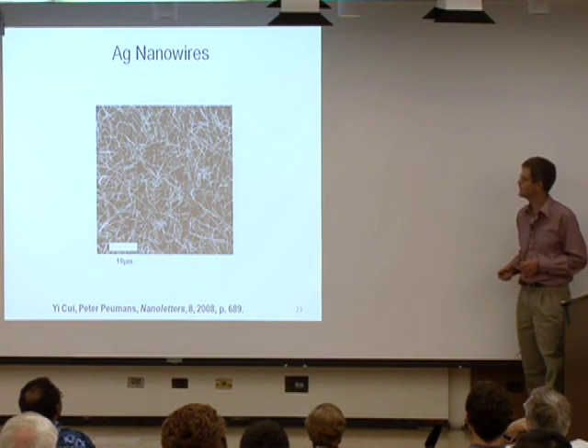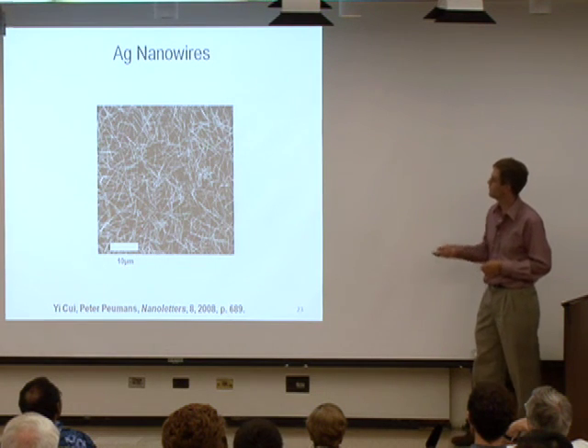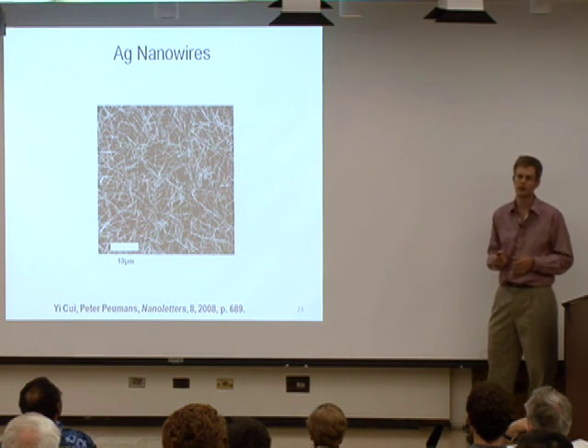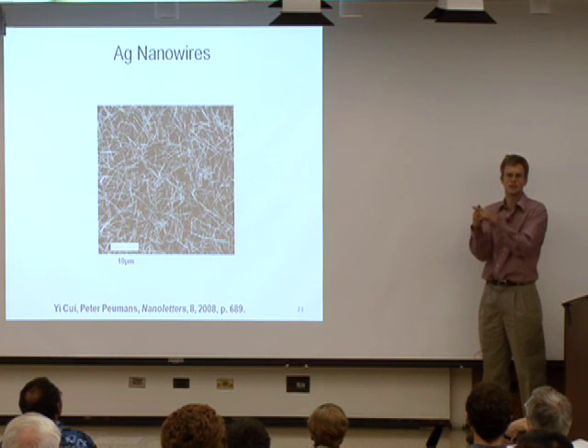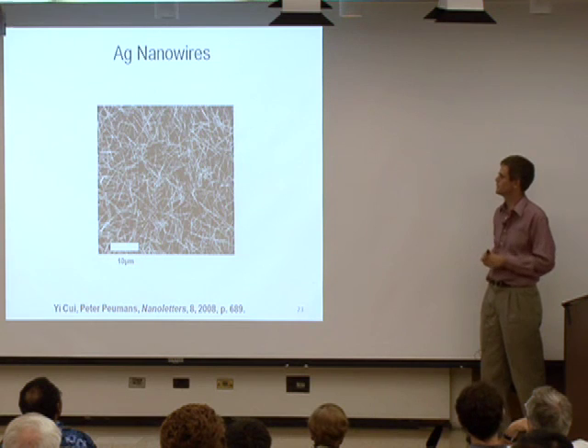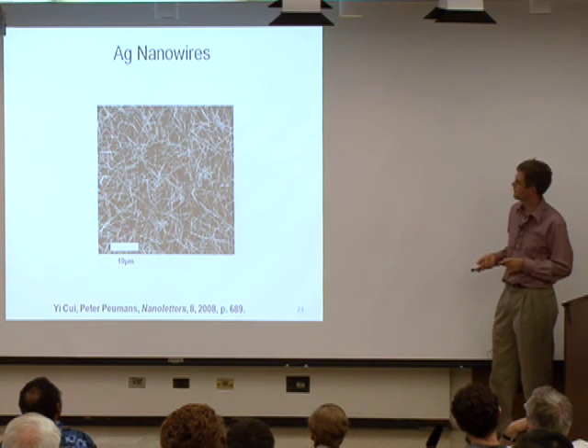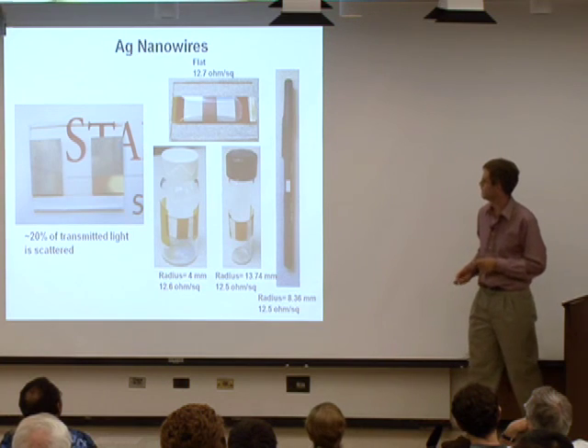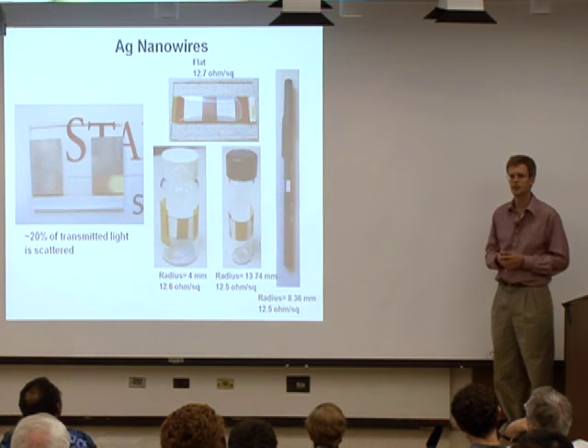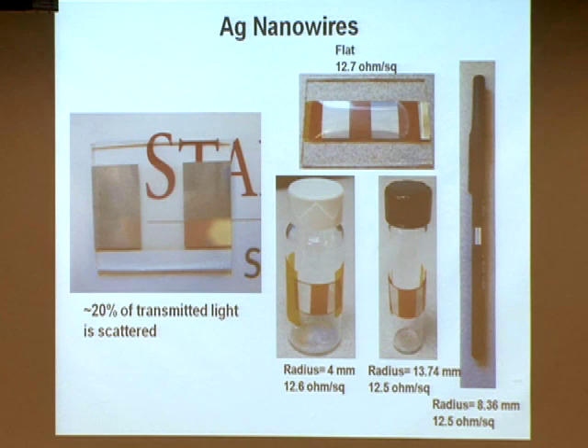Yi Cui and Peter Peumans have a similar approach. They are using silver nanowires, and the silver nanowires contact each other better than the nanotubes, and so that's one advantage they have. And they have recently shown that they can make films that have almost exactly the same properties as indium tin oxide. And you can see that these are highly flexible films as well. And the transparent part is right here in between two traditional metals. So you see that it's both transparent and it has a sheet resistance that's about the same as indium tin oxide.